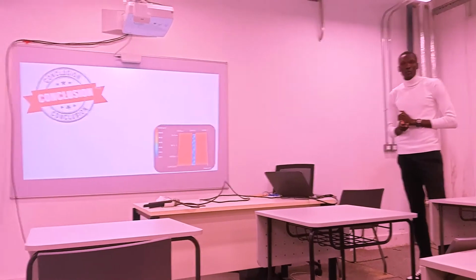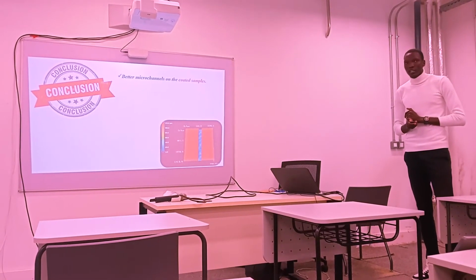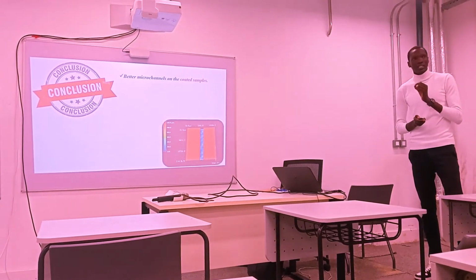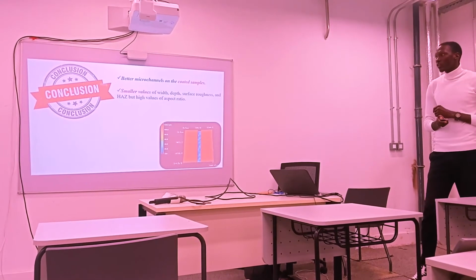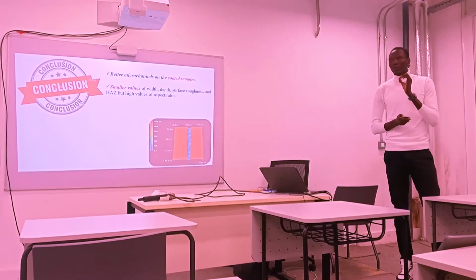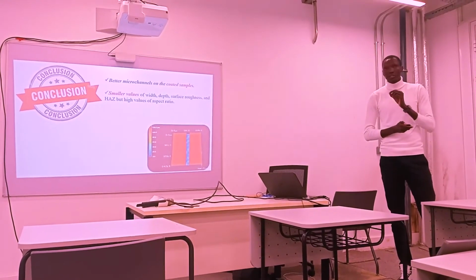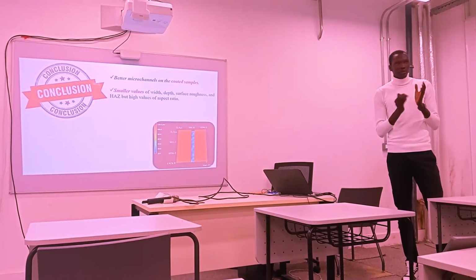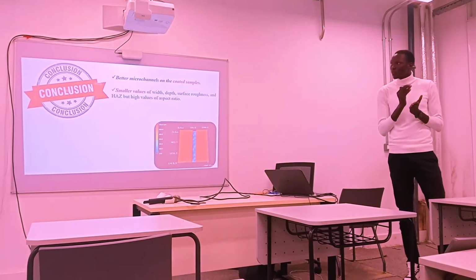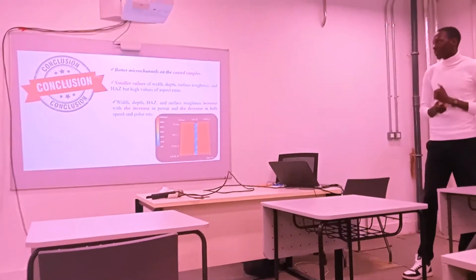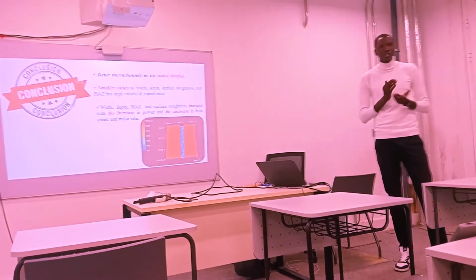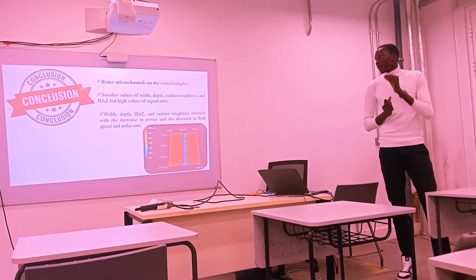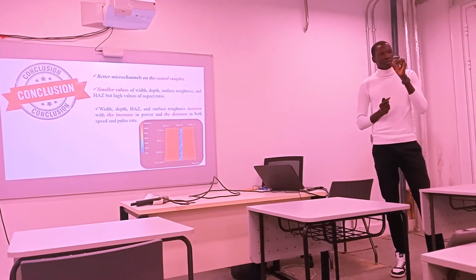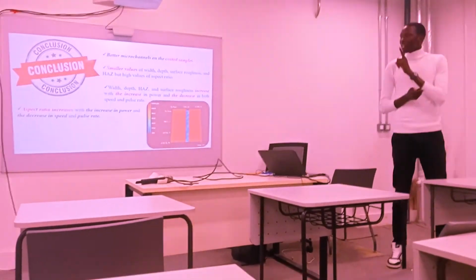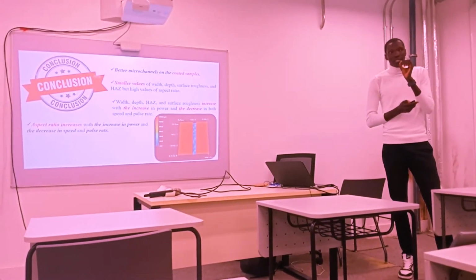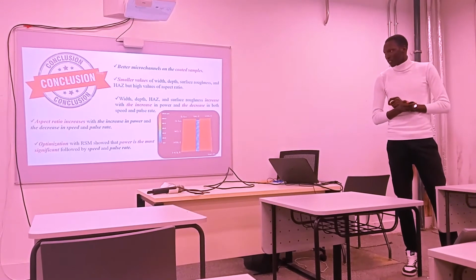What conclusions do we draw from this work? Number one, we got better microchannels with the coated samples, as we saw. Number two, smaller values of width, depth, surface roughness and heat affected zone can be obtained with coating. But when you coat, you get higher values of aspect ratio. The width, depth, heat affected zone, and surface roughness increase with the increase in power and the decrease in both speed and pulse rate. The aspect ratio increases with the increase in power, but decreases with the decrease in both speed and pulse rate.